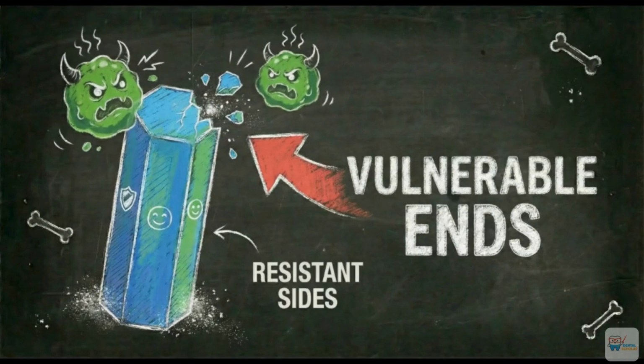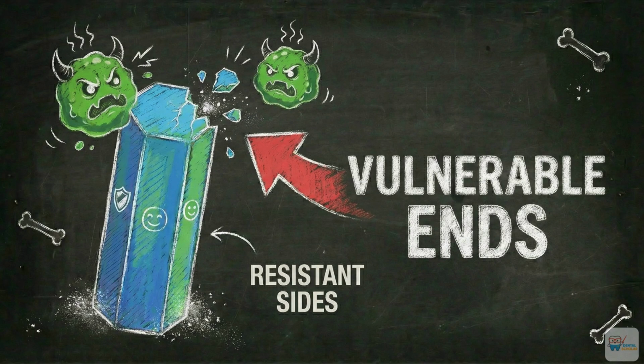Acid preferentially attacks the ends of the crystals, while the lateral surfaces are relatively resistant. See, hydroxyl ion is present at the core, that's why the ends are susceptible, whereas the surface is surrounded by calcium ions, and that's why the lateral surfaces are relatively resistant. This is a key concept in early caries dissolution.